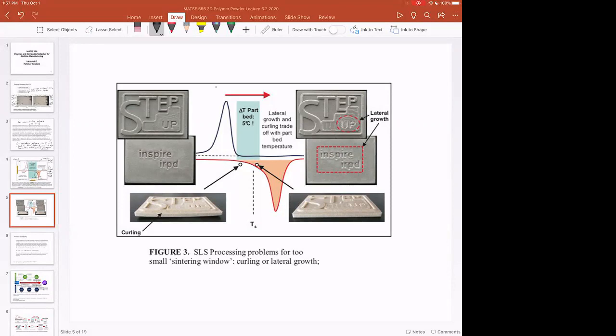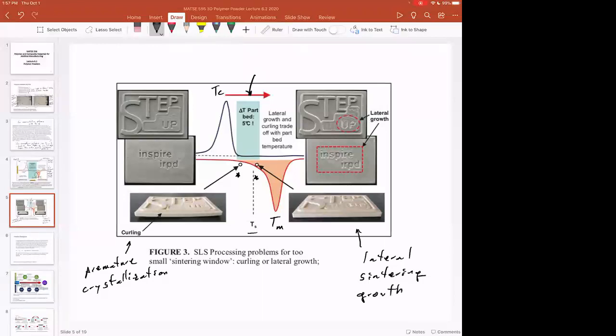so this is again TC and TM, and your sintering temperature is moving around between here and here. So if you're in the SLS region and you just change the part bed temperature by 5 degrees, in one case you can have curling. So this is premature crystallization. Whereas this is lateral sintering growth. And so you lose XY resolution if you're getting too much thermal diffusion.